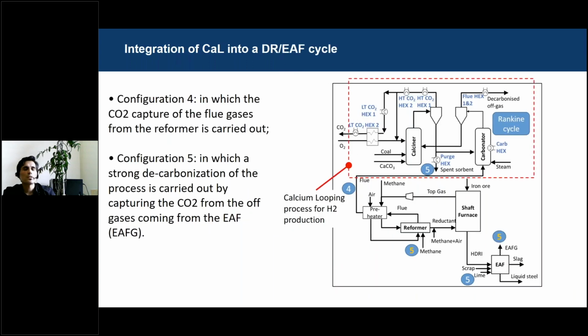Let's see also now the configuration of the DRI coupled with the calcium looping. We have considered configuration 4, which takes into account the decarbonization of the flue gas leaving the reformer, which produces the reductant. With this, we have considered also the 5th configuration, which takes into account also the decarbonization of the gas leaving the electric arc furnace into the reformer in order to replace a small part of methane. And also in this last configuration, we have used the spent solid leaving the calciner directly in the electric arc furnace because of its critical use.